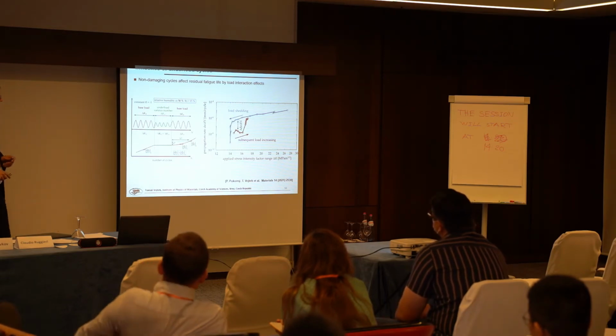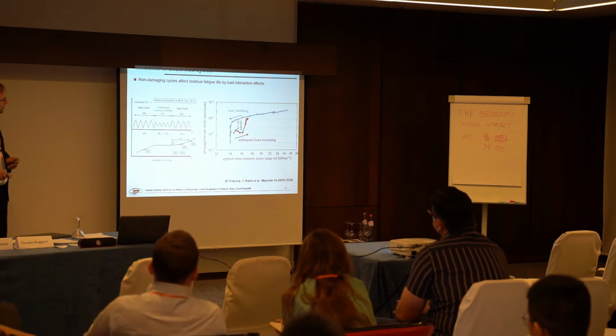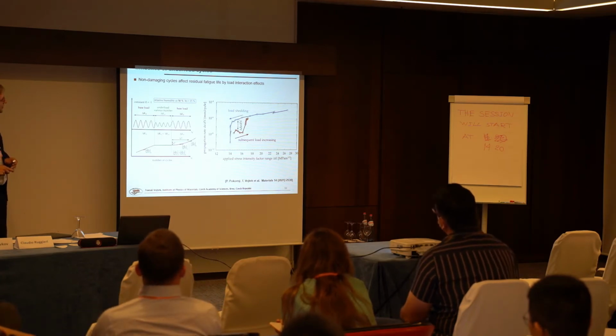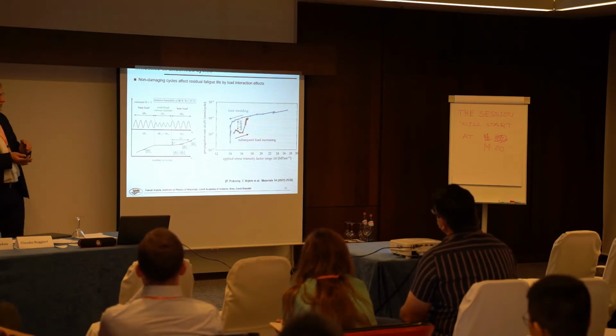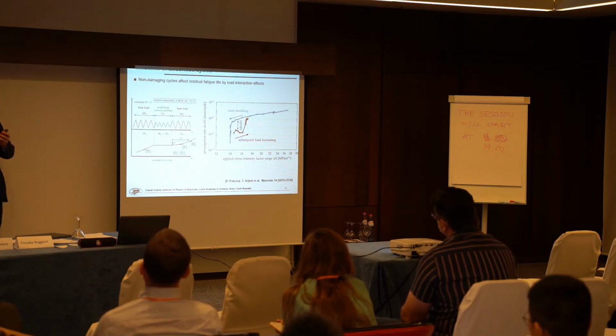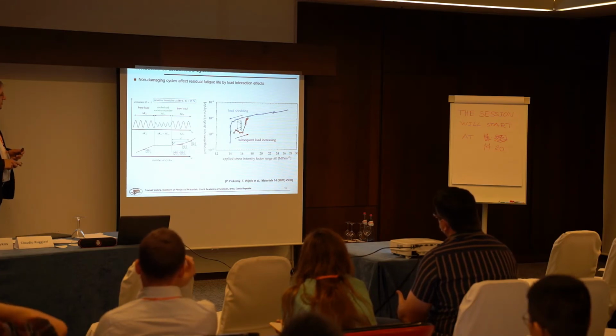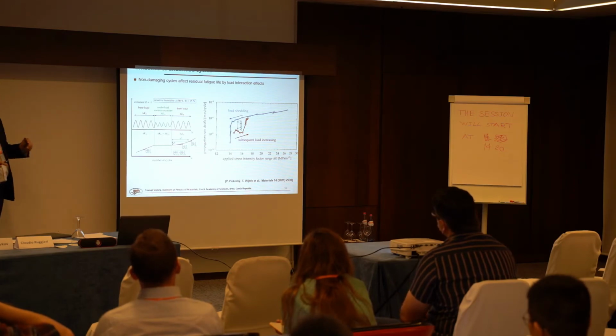And also there is an influence of underload cycles, which means that if you apply cycles that are below threshold, they are non-damaging, and usually they are omitted in the residual fatigue-life computations, but they have influence because of the oxide debris that is produced during those cycles, and it has influence on the subsequent crack propagation, which will be slower.